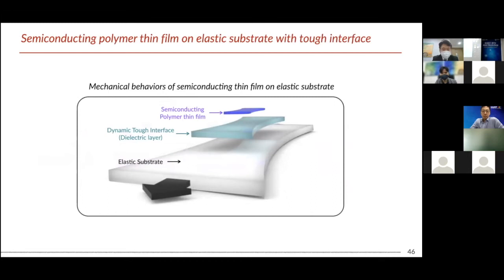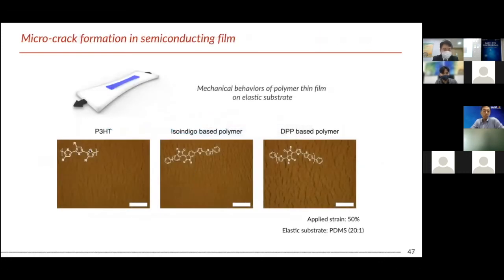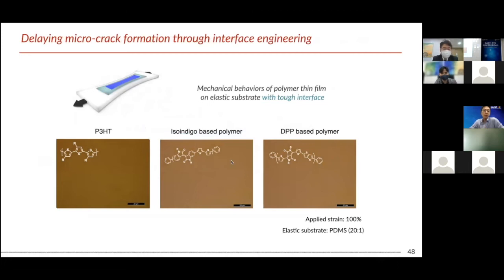So based on that, we started to look at how this interface can modulate the fracture mechanics of the polymer thin film. So we tried various kinds of semiconducting materials. If you simply laminate various kinds of semiconducting polymer onto the PDMS substrate, as you can see at 50% strain, there is a lot of micro crack formation. But surprisingly, we found that when we introduce the tough interface, they couldn't show any crack formation even at 100%.